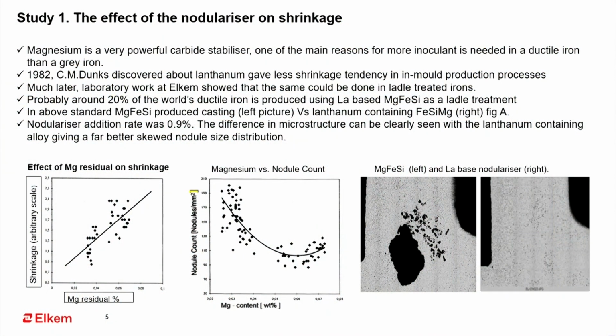Another disadvantage is that residual magnesium is a very strong carbide stabilizer. When your residual magnesium level is high, there are definite chances of getting carbide. And high residual magnesium also creates a low nodule count. So that factor we have to consider when making safety critical components of ductile iron. Lanthanum based ferrosilicon magnesium was developed in 1982.